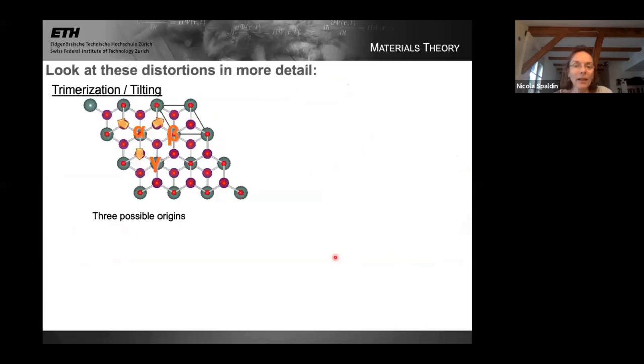I want to look in a little bit more detail at these distortions, this tilting. The first thing to notice is the tilting has three choices of origin around which it can occur. So here's the top of one of those pyramids. Let's say it trimerizes with this oxygen going this way, this one going this way, and this one going this way. So it's choosing origin alpha